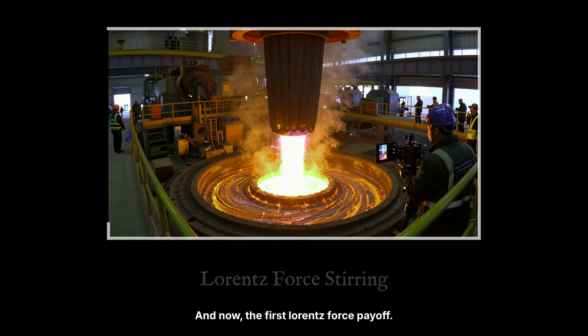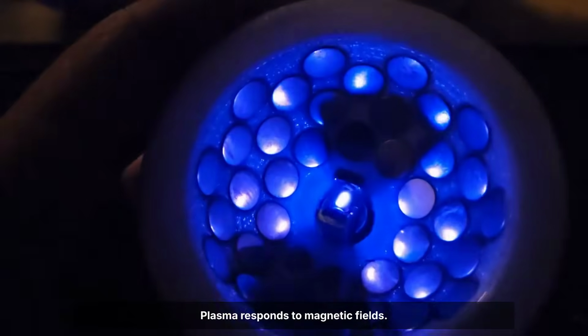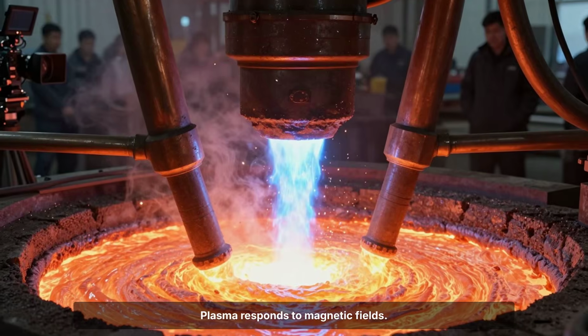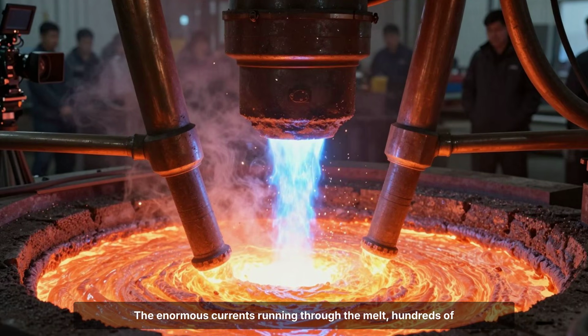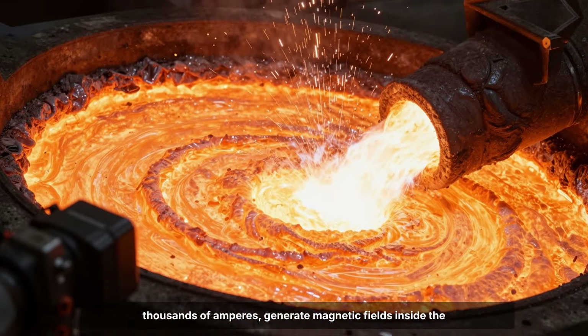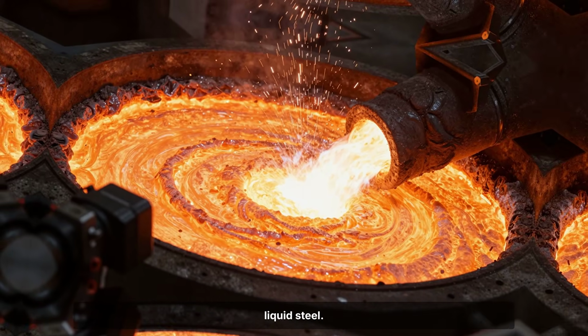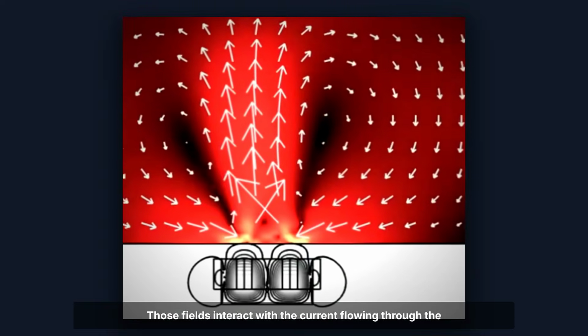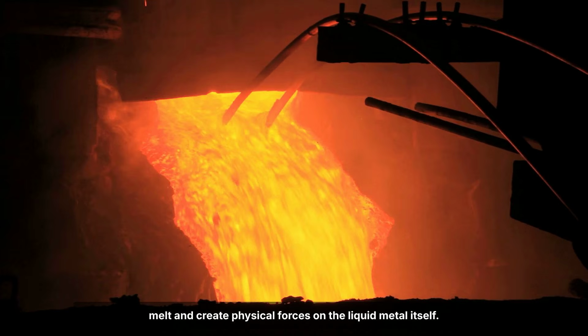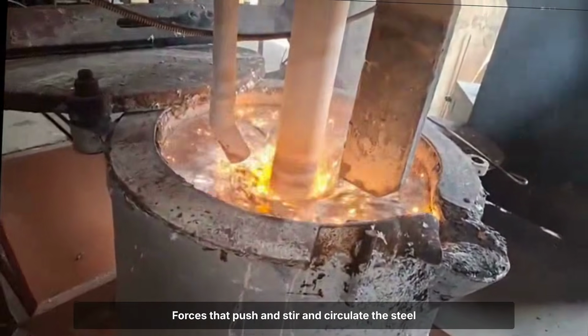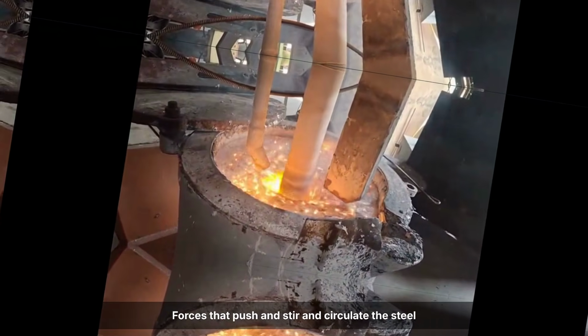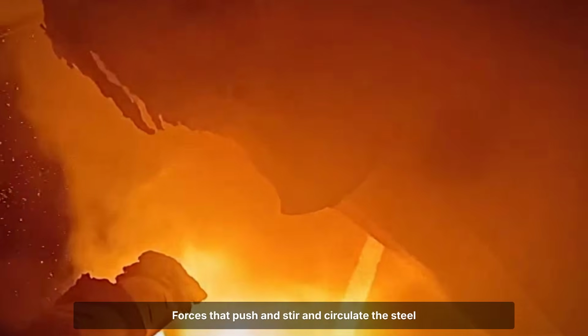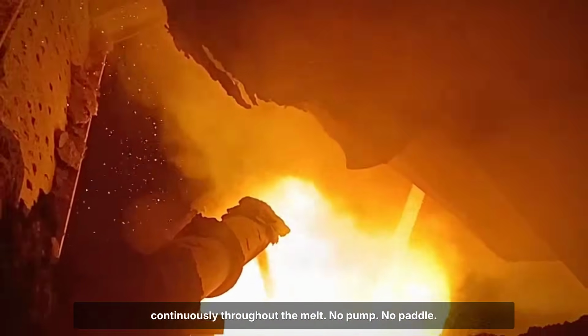And now, the first Lorentz force payoff. Plasma responds to magnetic fields. The enormous currents running through the melt, hundreds of thousands of amperes, generate magnetic fields inside the liquid steel. Those fields interact with the current flowing through the melt and create physical forces on the liquid metal itself. Forces that push and stir and circulate the steel continuously throughout the melt.